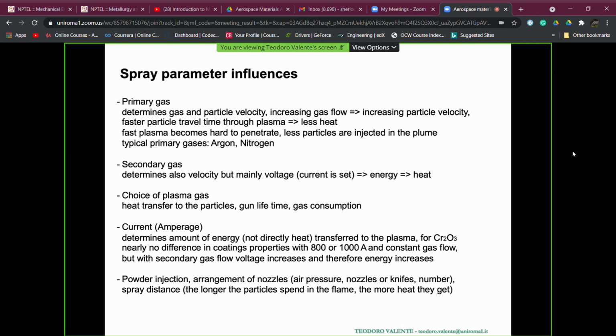And it's important because it is also related with the spray distance, which is another important parameter. As we have already said, the longer the particles spend inside the plume, inside the flame, the more heat they get. So the highest degree of melting can be obtained without exceeding, in order to avoid going into evaporation phenomena, which affects, first of all, low melting elements, and can change the coating composition.